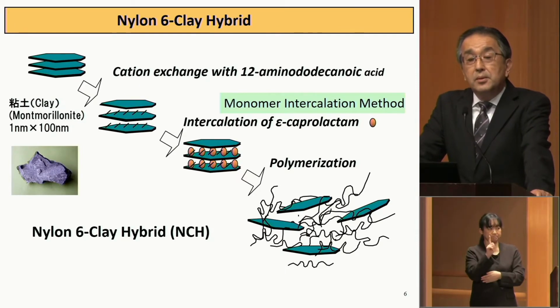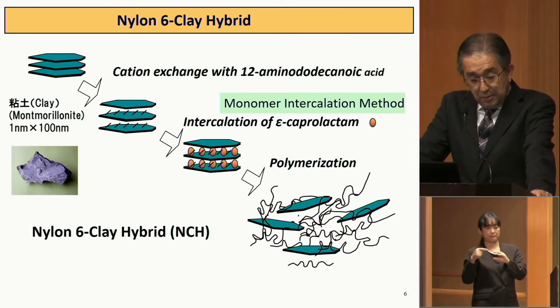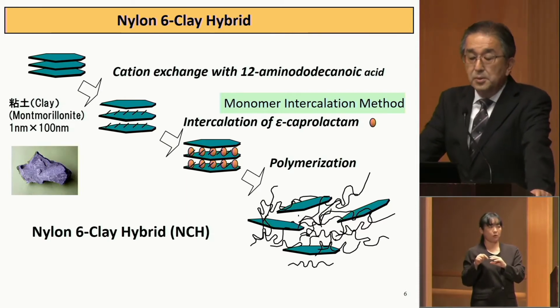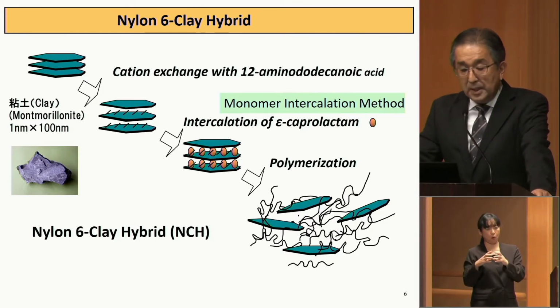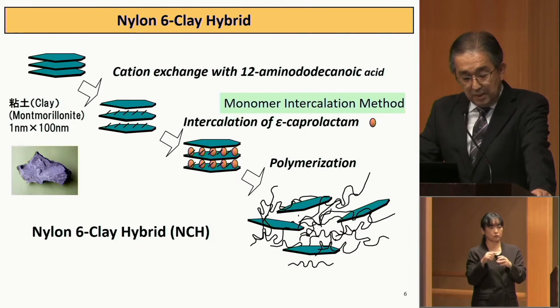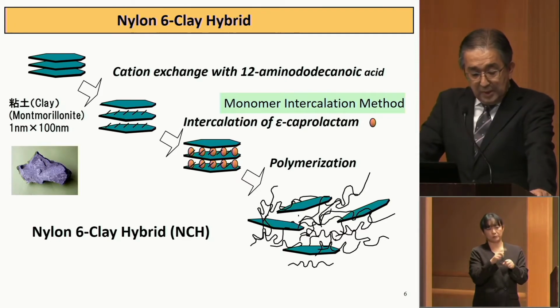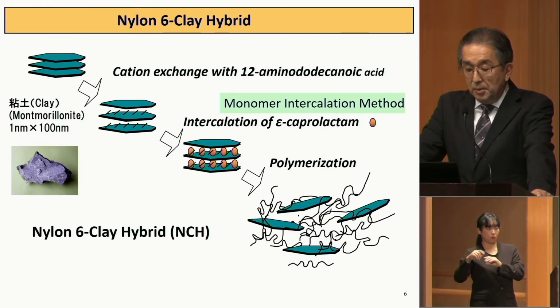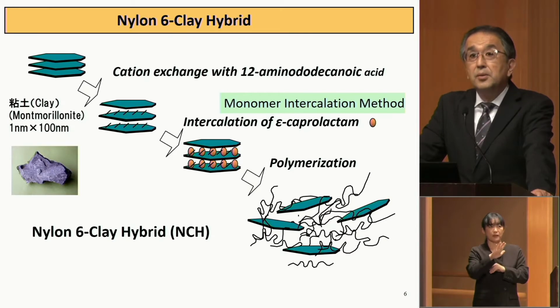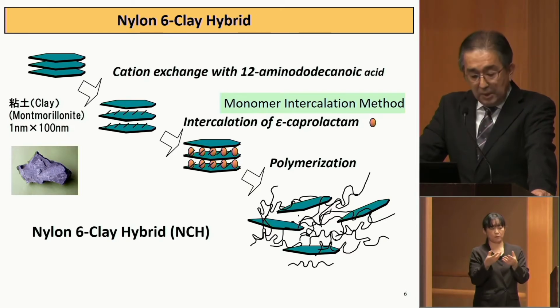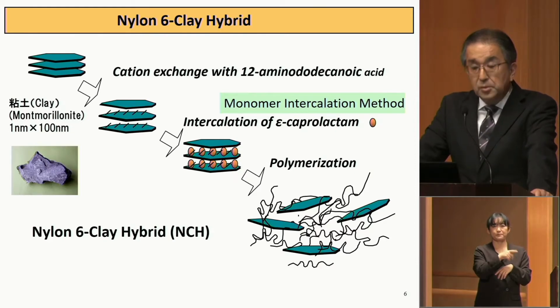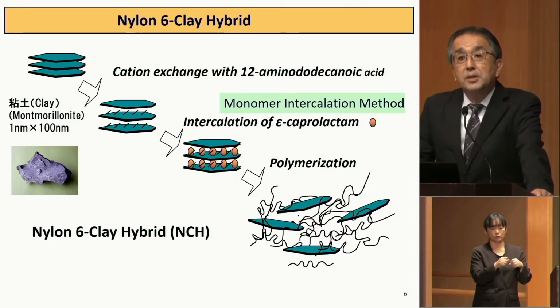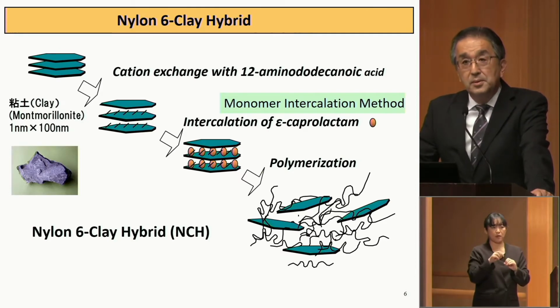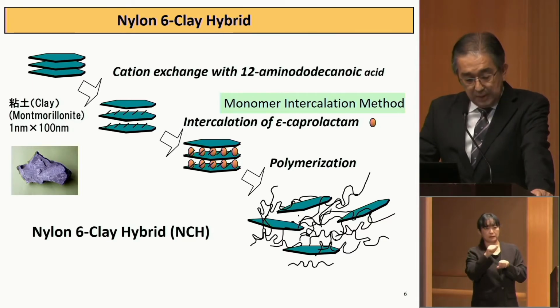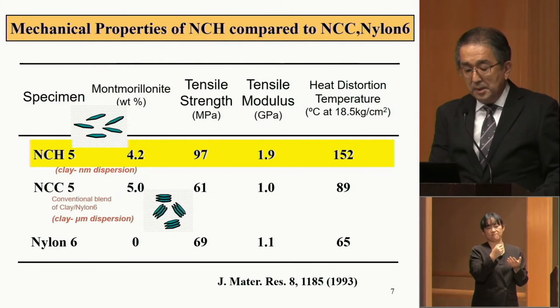This slide shows the scheme of how nylon 6 is synthesized. Starting from upper left, clay has layers. The nylon 6 is synthesized in between the layers. Sorry, again, it's very technical. By cation exchange with 12-aminododecanoic acid, intercalation of a monomer, epsilon-caprolactam, and polymerization, clay is dispersed in the polymer at the nanometer level. This scheme is very simple, but a good material can be generated. That's what we obtained back then.